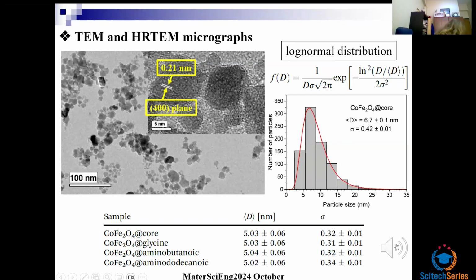And on the lower part of my slide, you can see a collection of particle size, mean size, and size dispersity. So this has to do with a typical synthesis, and we can see that the data extracted from the TEM and curve fitted using the log normal distribution provides about the same size of the core regardless of the surface coating, and about the same particle size distribution. So this is a very important point, meaning that the surface coating does preserve the core of the nanoparticles in terms of crystal structure and in terms of mean size.